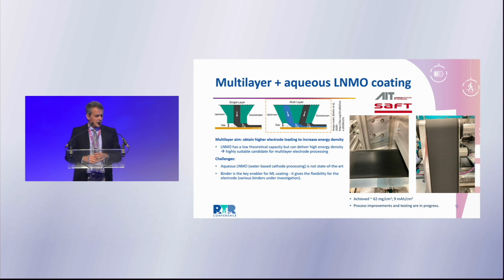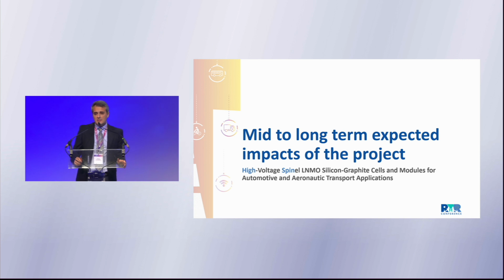We have modified our machinery at the pilot line, and we have developed the methods to double coat the electrode. In this way, we can achieve almost double the areal loading for the cathode. The process is not yet error-free. What you see on the slide in the picture is the electrode that has been coated, and you can see these small dots, these are small bubbles. So we're working on refining the process and upscaling the process. And this can also provide quite a bump in increasing the performance that we can extract from this technology. So these are the results that I wanted to present today.